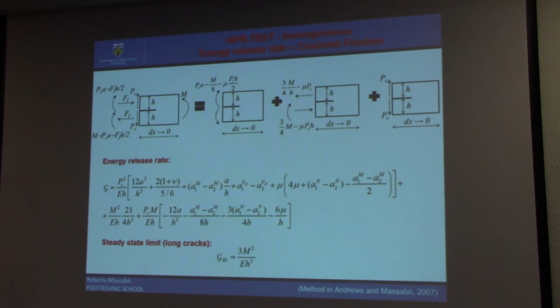Then we can apply the technique to calculate the energy release rate. What we did, we applied the methodology originally proposed by Suo and Hutchinson that was modified by Thouless and by Andrews and myself to account also for the presence of shear. And we were able to define this analytical expression for the energy release rate, which depends on the applied loading, on the contact force, on the geometry, and on all the compliance coefficients for root rotation and root displacement. And again, when the crack is long enough, we are approaching the steady-state limiting solution.